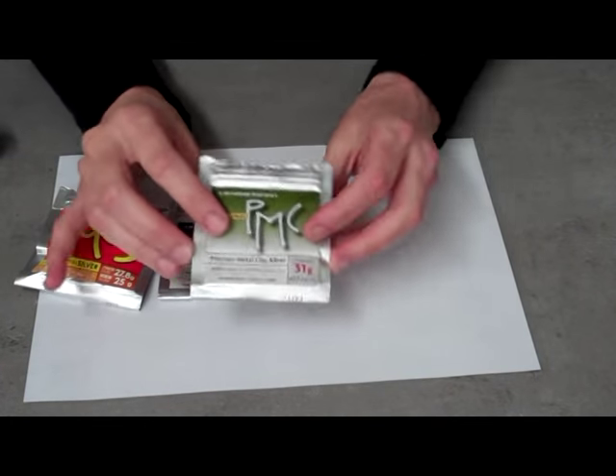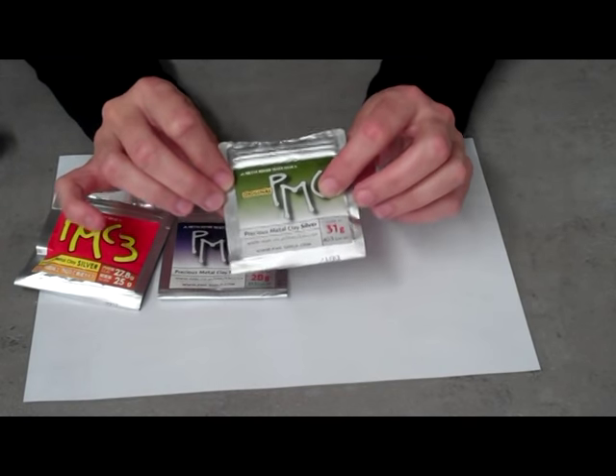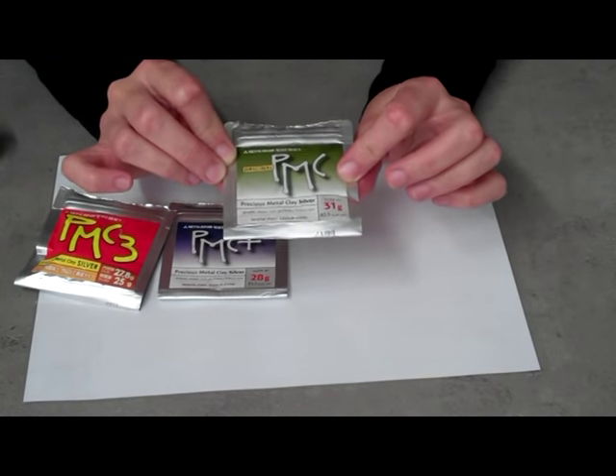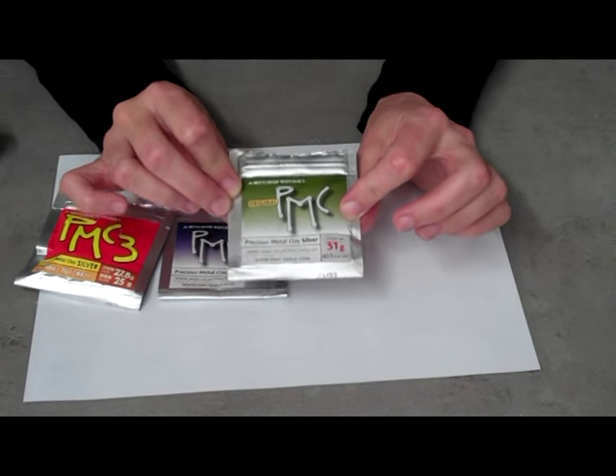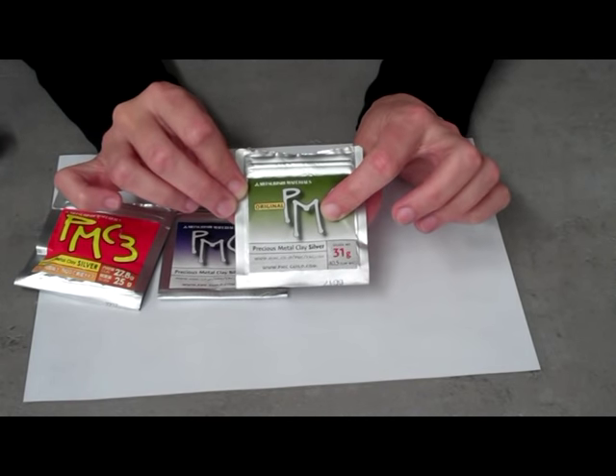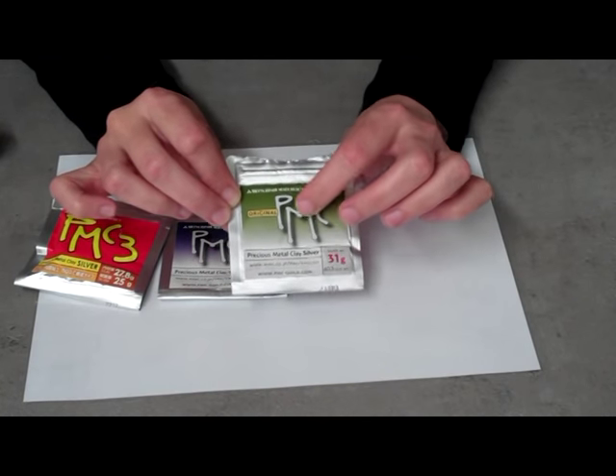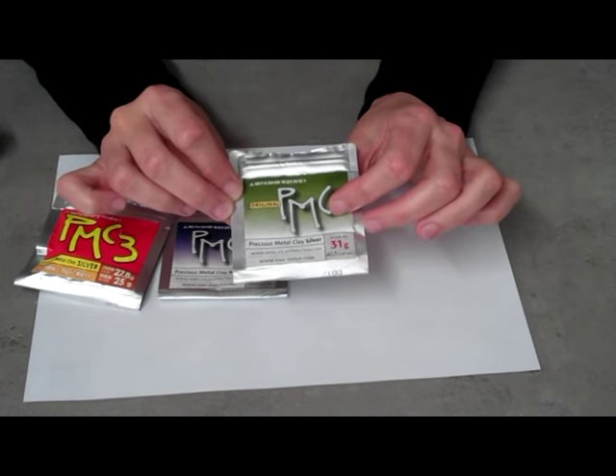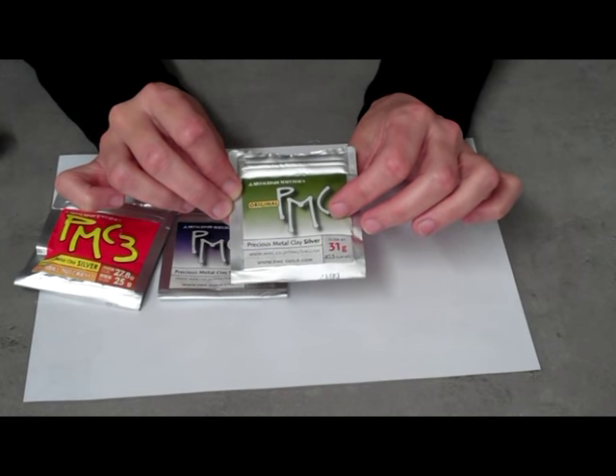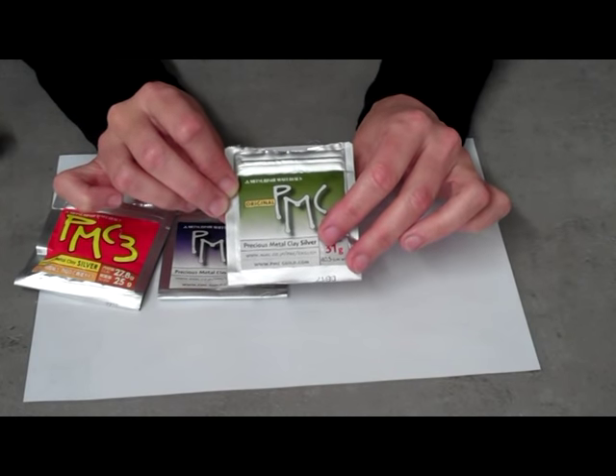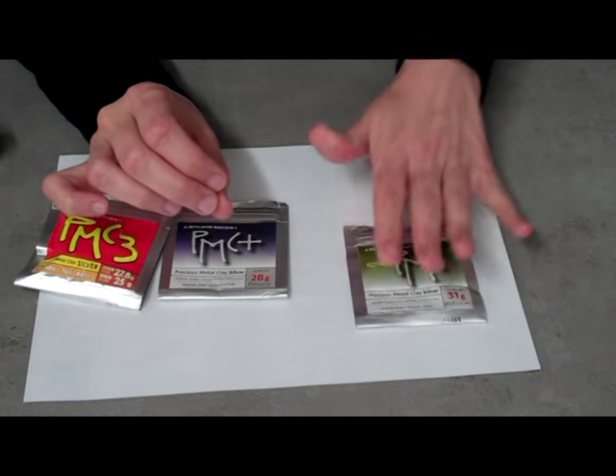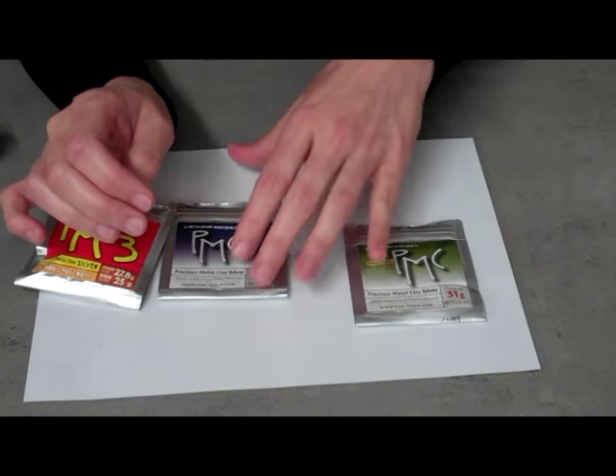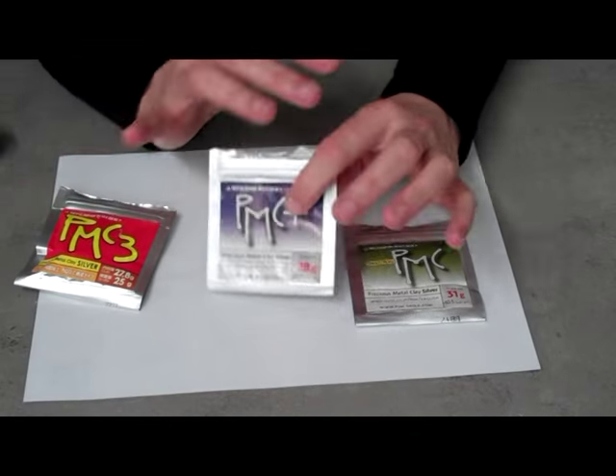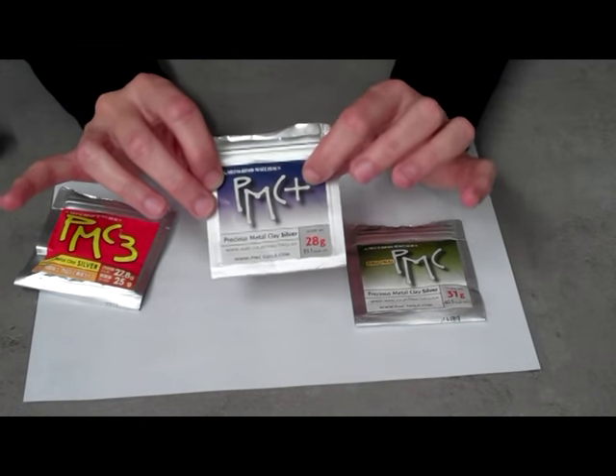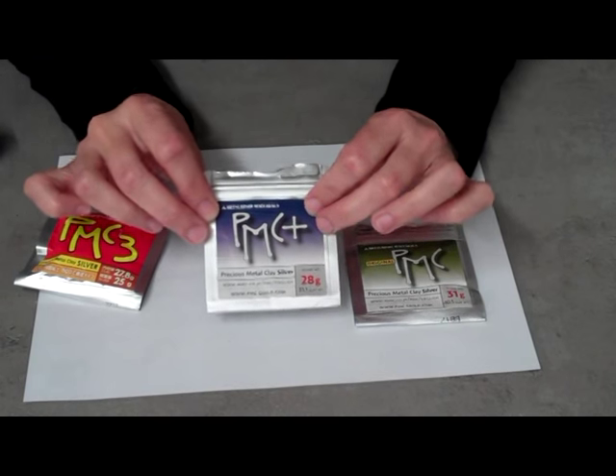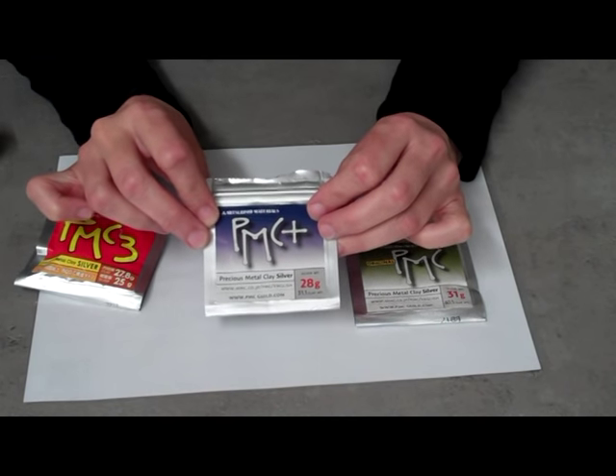Initially, the very first PMC was the PMC Original, or Standard as it's sometimes called, was the very first product out, and this has to be fired in a kiln. You can't torch fire this unless you want to fire it for a very, very long time. And this shrinks by between 28 to 30%. And that was the very first clay that was available, and the scientists at Mitsubishi, which is the company that produced PMC, then went on to produce PMC Plus, which can be fired with a torch or in the kiln.